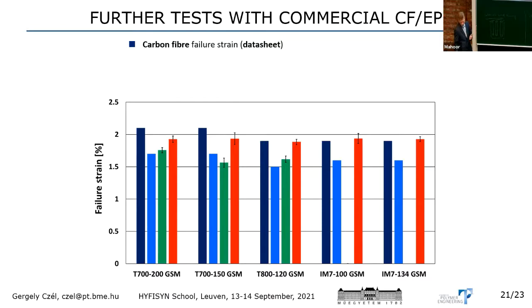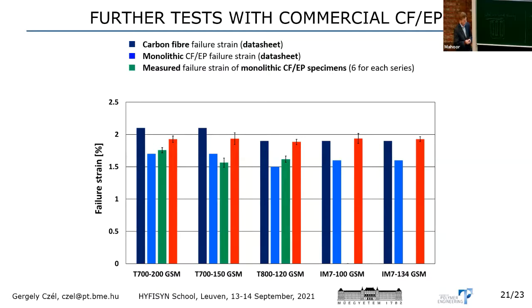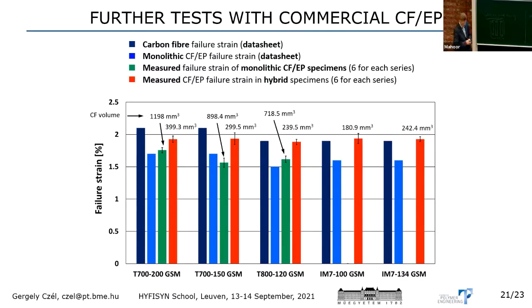columns, but this is for the fibers. Then datasheet values for the monolithic carbon epoxy composites. Then measured failure strains, our own measurements for monolithic specimens, and then measured values for the hybrid specimens. And for reference, I also included the volumes, which do not match too much, but you can at least see that there is no orders of magnitudes difference, where we would start to see effects due to the different volumes. So, okay, it's like 4 times, but not 100 times bigger for the 2 different specimens.